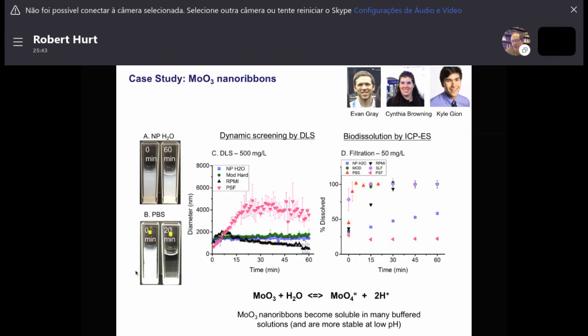And the added benefit of this material is that when molybdenum trioxide dissolves into soluble products, those soluble products, molybdate ion, is not particularly toxic in its own right. So the shape goes away and the soluble products are relatively safe under most doses, making this material something that we think could be safely developed.